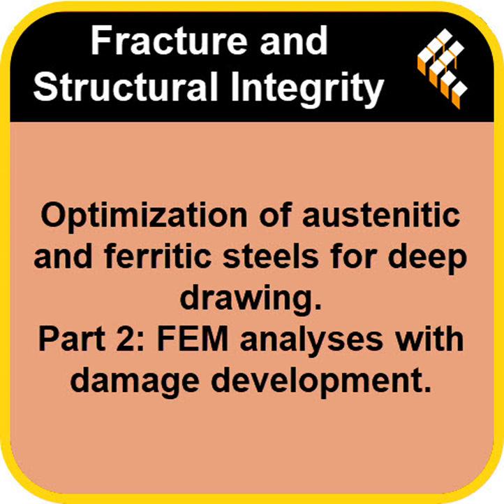It unlocks insights you just can't easily get from physical tests alone, like seeing exactly how the thickness evolves second by second or mapping the stress distribution. The FEM clearly showed how the 304 steel, with this better work hardening, spread the stress out much more evenly than the 430.